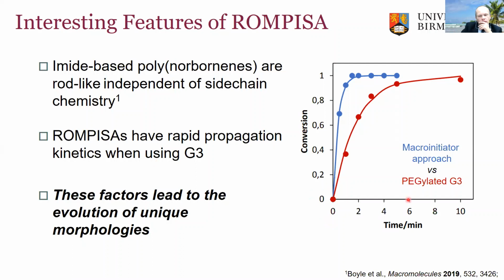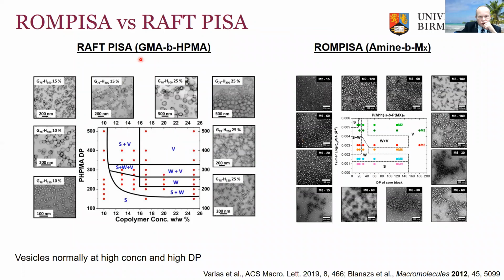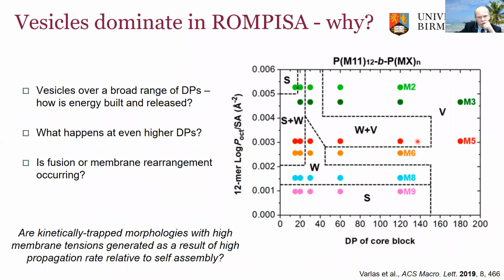If we just use the conventional pegylated G3, which is the conventional approach for aqueous ROMP, with our macro-initiated approach we're now seeing very fast kinetics, and this actually leads to the evolution of quite unique morphologies. If we very briefly compare the RAFT PISA phase diagram with the ROMP PISA phase diagram, in RAFT PISA we really only see vesicles or polymersomes at high concentration, high DP. If you look at the ROMP PISA, you'll see that the vesicle window is much larger. We see higher order structures, and we propose this is in part due to the rod-like nature of the polynorbornenes, which when packing within assembled structures disfavors higher curvature structures such as spherical or worm-like micelles and favors polymersomes.